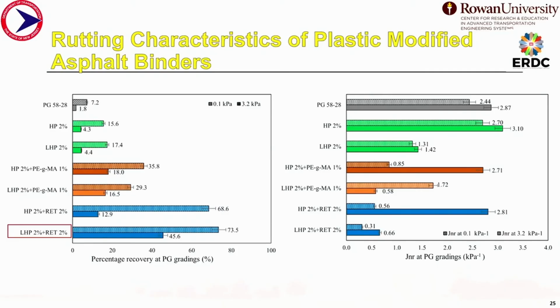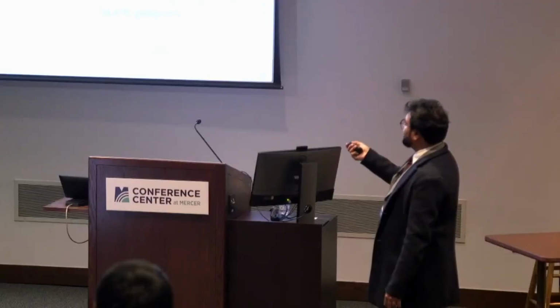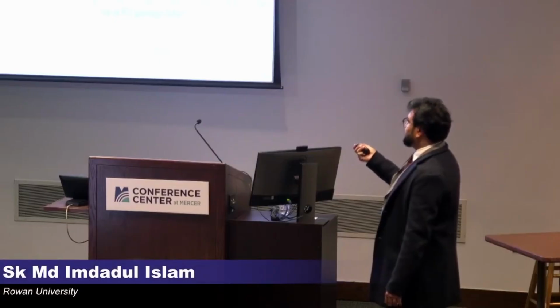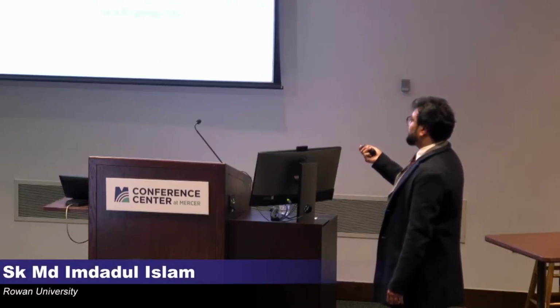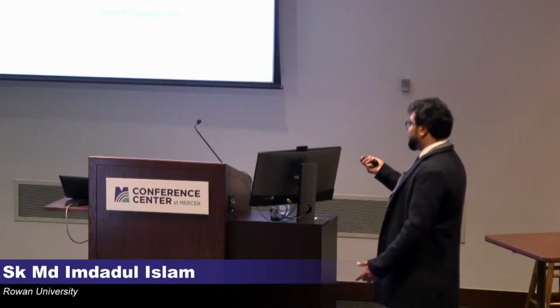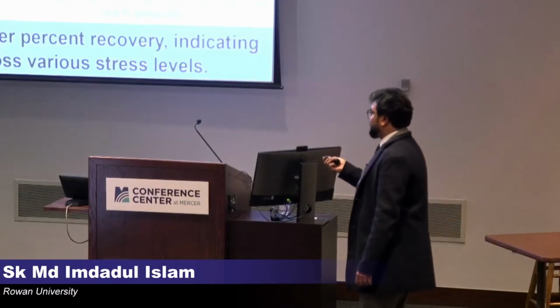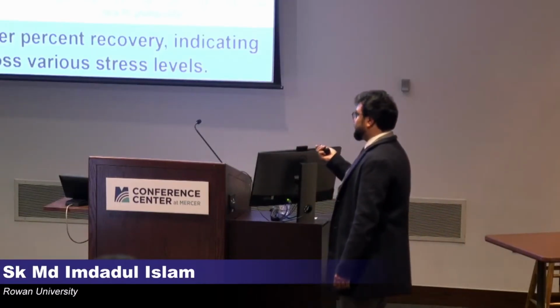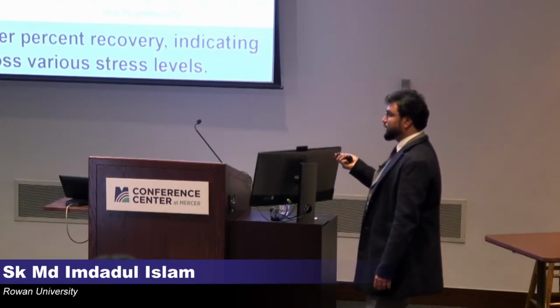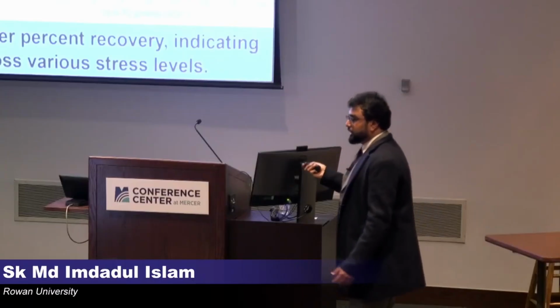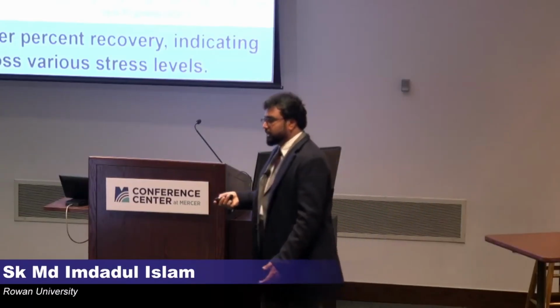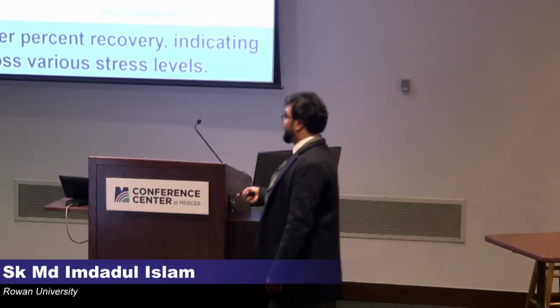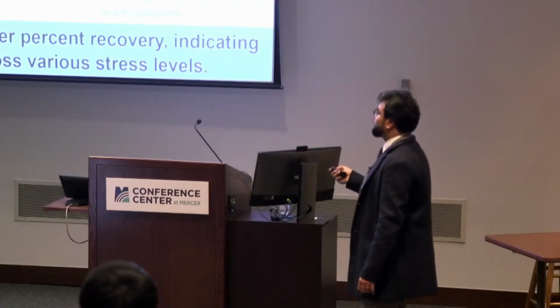On the other hand, the lower the JNR value is, the better the performance will be in rutting resistance. So here we can again clearly see the LHP with the RET is showing the lower JNR value than the HP or RET combination. From here, we can again say that the RET exhibited the lower JNR and higher percentage recovery, indicating that it enhances the rutting resistance across the various stress levels, as we did the test at 0.1 and 3.2 kilopascal.